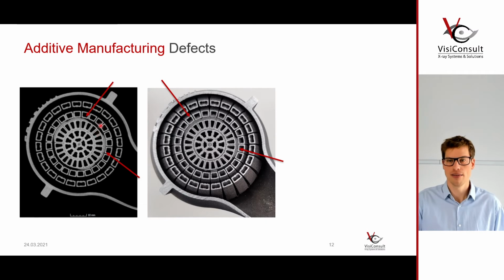And what we've done here is on the left side, we performed a non-destructive CT scan, and you can nicely see that it's clogged here, it's clogged in the middle. There's a lot of residual powder. After it was cut, we could see, whoops, it really is there. Of course, while cutting, it got loose and removed a little bit. So CT can help you very, very well to find this residual powder and make sure it's not inside.